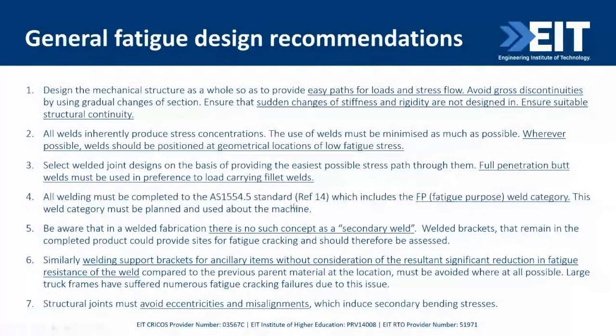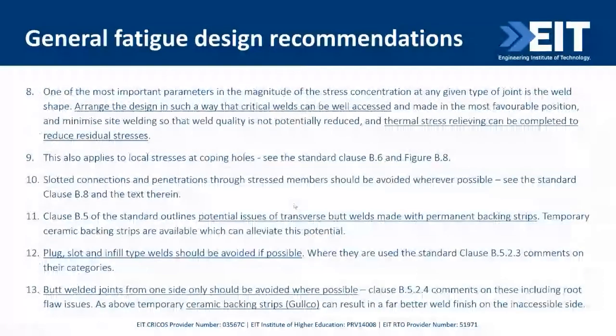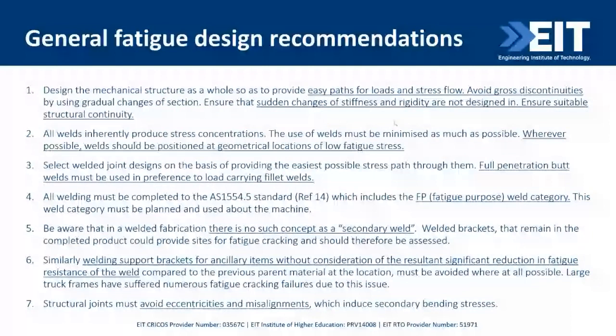Okay, so this is another 3 slides with too much text, but the fatigue recommendations are basically you must have easy load paths for load and stress flow, no gross discontinuities, fair structural continuity of everything into the rest of the structure, welds positioned at low stress locations. Forget about fillet welds. They've all got to be full penetration T or straight butt welds. The 1554 code, and there's no such thing as a secondary weld. So you've seen truck chassis with don't weld here. That's all that is about.